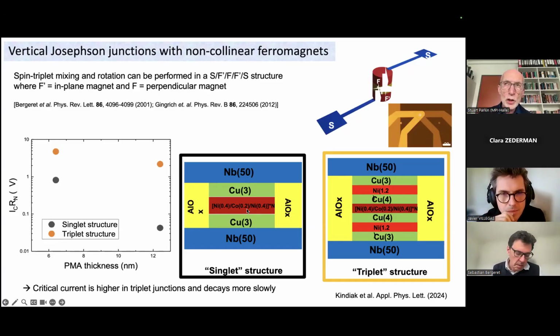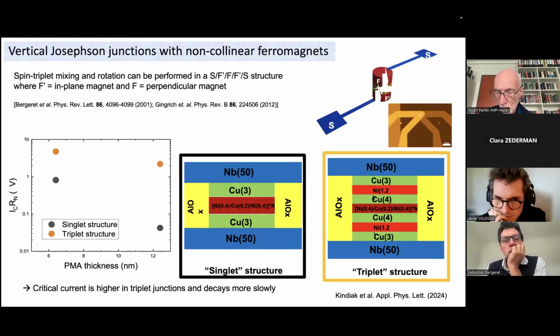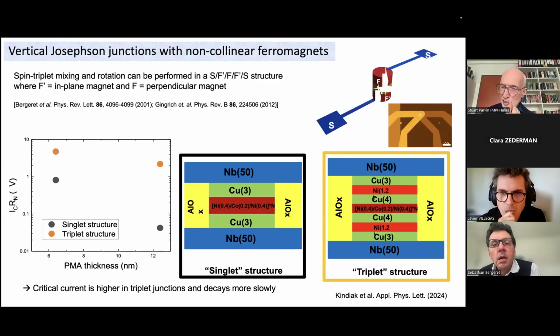In fact, these nickel and cobalt layers, a few angstroms thick, are essentially identical to the cobalt-nickel sandwich I mentioned earlier in the racetrack. So this is derived from our racetrack. Essentially, we have a racetrack separating two niobium electrodes, but here we're not considering domain walls. The racetrack here is magnetized all in one direction. Now, the idea is we can pass a supercurrent from the niobium top electrode to the bottom niobium electrode through the copper and the nickel-cobalt multilayer.